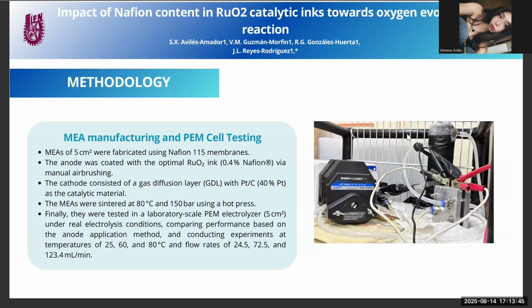For the electrolyzer test, we used NAFION 115 membranes and coated the anode with the optimal ink via manual airbrushing. The cathode was a platinum carbon catalyst layer. Membrane electrode assemblies were hot pressed at 80 degrees Celsius and 150 bar, then tested at different temperatures of 25, 60, and 80 degrees Celsius, and flow rates of 24.5, 72.5, and 123.4 milliliters per minute.